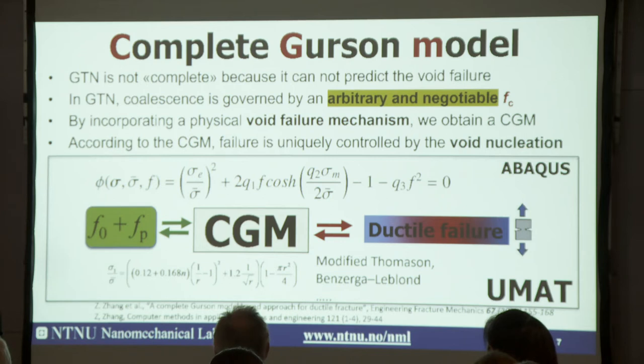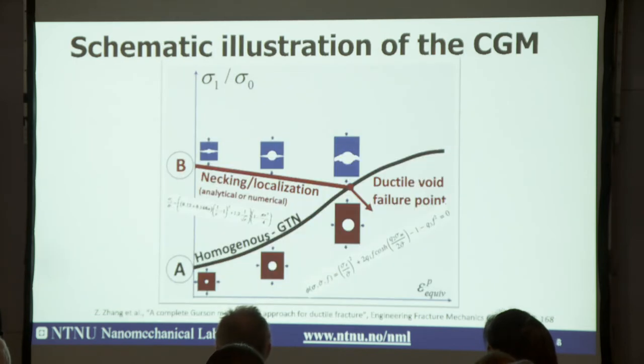You are not done with the complete Gurson model yet, so I want to bother you with one illustration. This is an illustration of the complete Gurson model. Think about it, you have a void in the center of a unit cell. Then you have two deformation modes, or two deformation paths. The first one is a homogeneous deformation path. That means the plastic flow around the void can be homogeneous, the plastic deformation can go anywhere as necessary. This behavior can be described by the homogeneous path like the GTN model.